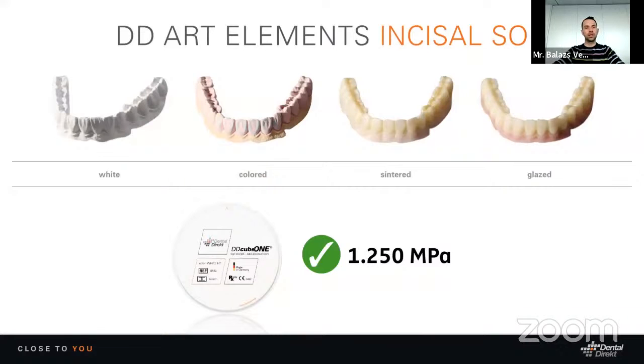And here is, at last, an example of a case that you can solve easily from a white material. In this case you see an implant case, a directly screwed implant, where the gingival part was also restored. We started from a white zirconia. We had to color the gingival part with a pink color, with some characterization. After the sinter process and the glaze process, we reached our final aesthetic restoration.